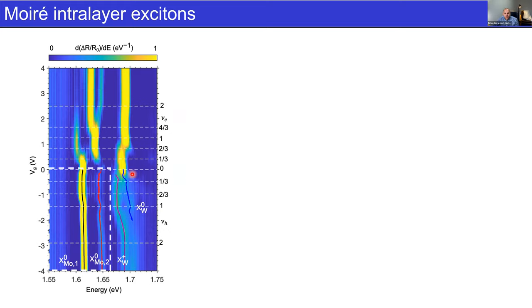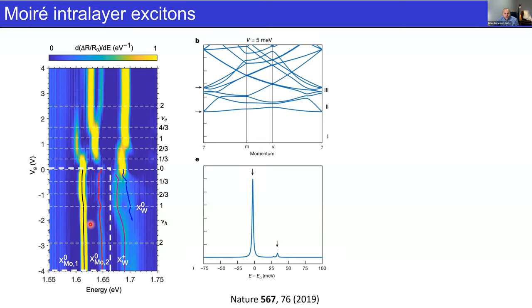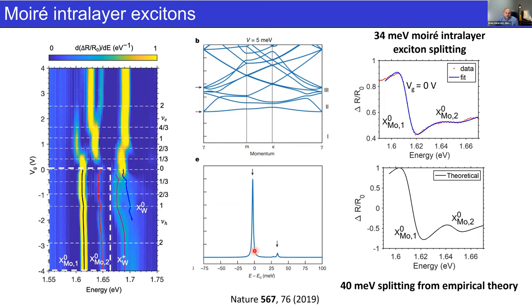And what I want to focus on in the next just a couple slides is the p-type doping and the assignment of some of these peaks. So we see that there are essentially two peaks associated with the tungsten diselenide A exciton, which we believe are two Moiré excitons, similar to what was reported by Feng Wang's group in this paper, where basically, and we can apply sort of an empirical theory, which basically includes just the Moiré periodicity and the potential of the confinement. And we end up with a fairly good agreement.